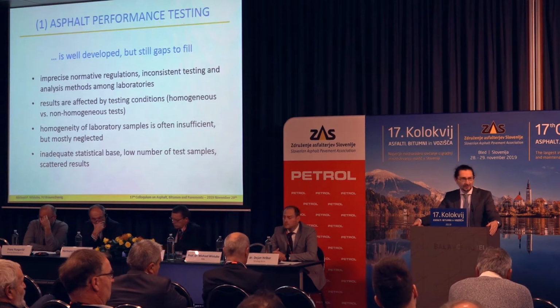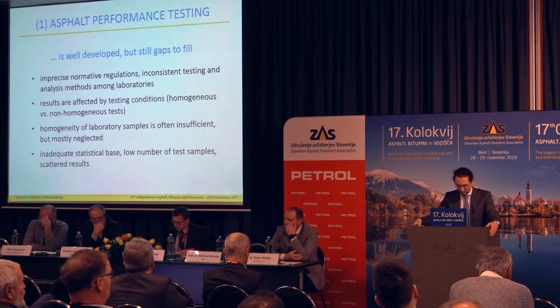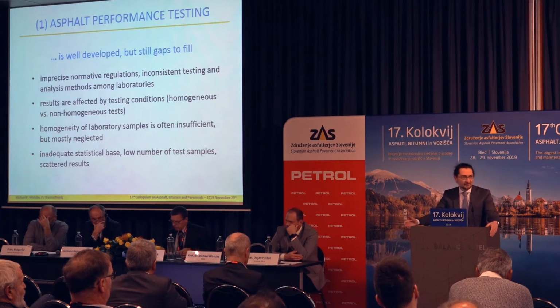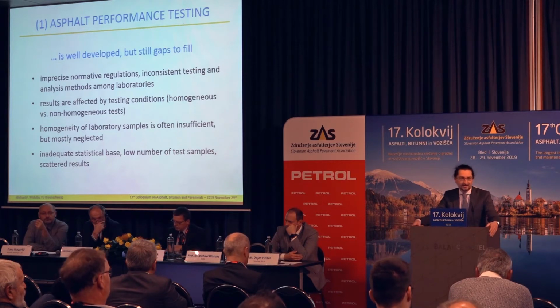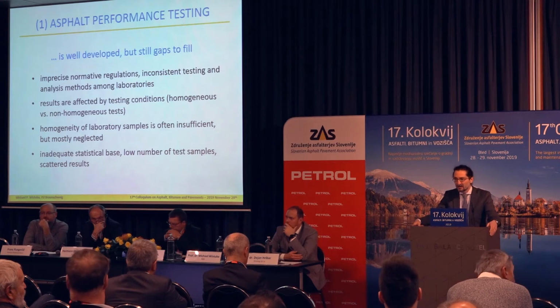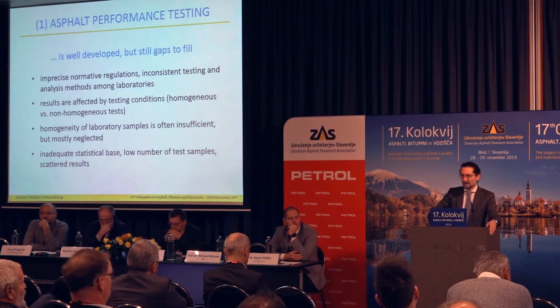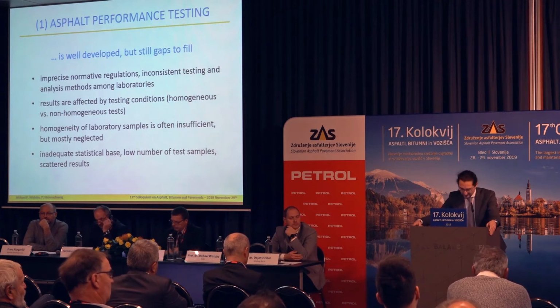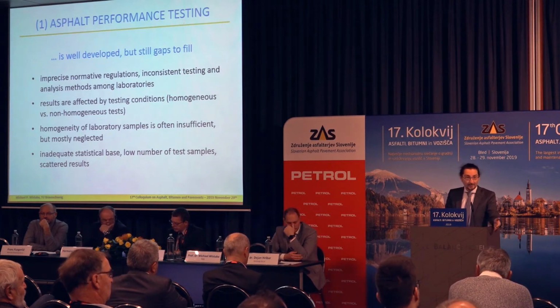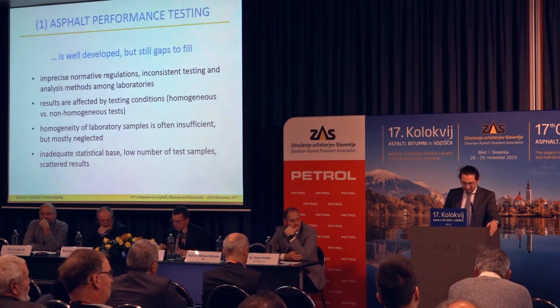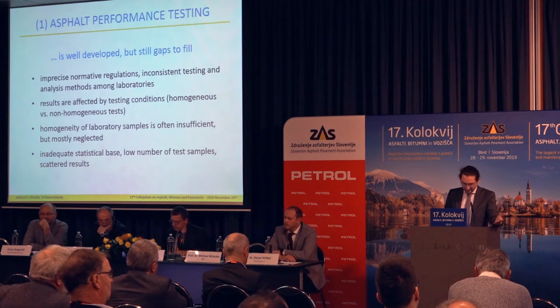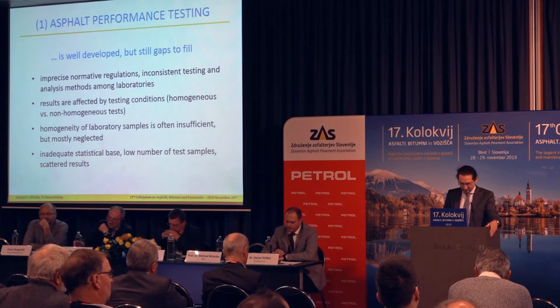And in the end, because the tests are rather complex and elaborate, we just do a limited number of tests for any material, maybe 3, 5, 10 samples, but that's it. And so the statistical database is not enough to derive really solid and sound results. So there are a lot of things more to do to make this way of testing asphalt mixtures better.